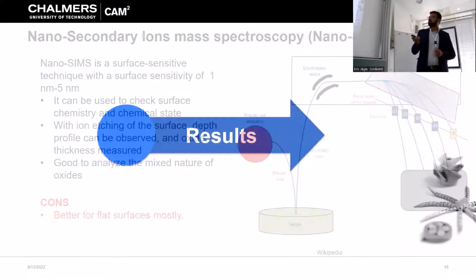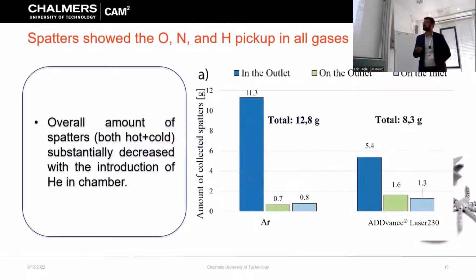Okay, so let's move on to results. Yesterday Sophie showed that the amount of sputters, which she showed through OT, is decreasing with the introduction of helium. There was a question whether they are only cold sputters or hot sputters, because helium has very good heat conductivity, so they cool very fast. Here we found that the total amount of sputters decreased, both cold and hot. So with the introduction of helium, the amount of sputters can be decreased significantly if you compare both values.